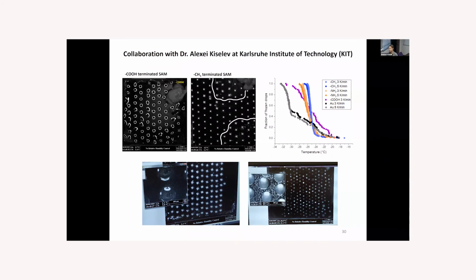So what we've done until now with these self-assembled monolayers of alkanethiols is that, thanks to the collaboration with Dr. Alexei Kiselev, I showed you his science at the beginning of this part, and based on that we were doing parallel studies on the feldspars, so we started a collaboration. They have a very nice system they made at the Karlsruhe Institute of Technology, where they can automatically dose many droplets of water of a selected size on the surface, and can record the freezing of these water droplets as a function of time and temperature, and automatically the program draws curves of freezing as a function of the temperature.